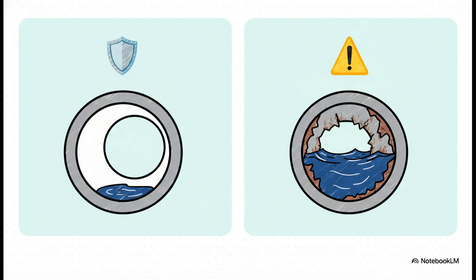And here's the really uncomfortable truth about field life. A pipeline that gets validated as perfectly safe in year 1 can silently become a massive liability by year 15. When a well is fresh, you've got high pressure and a low water cut, meaning there just isn't much water in the fluid mix. But as that reservoir matures, the pressure drops and the water cut climbs. From topside, production might look completely normal, but deep inside that pipe, the risk profile is shifting dramatically.